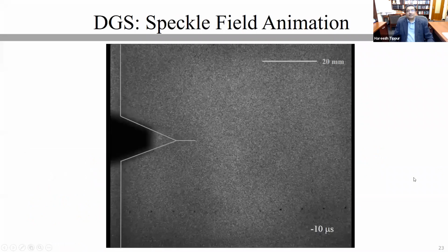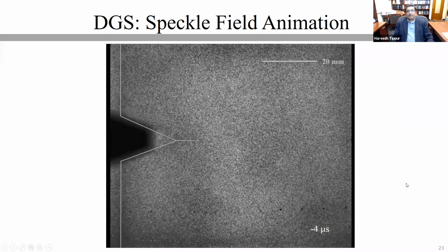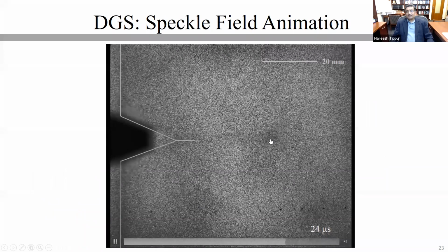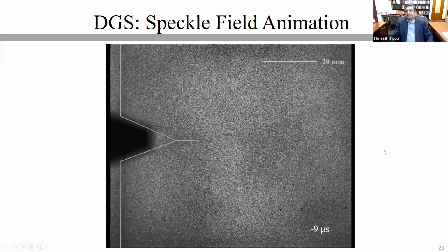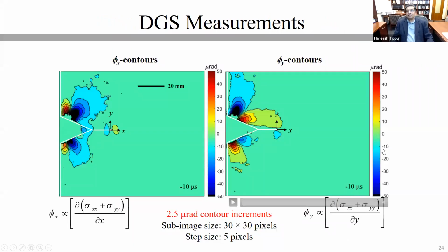Let me show you a little movie of the animation that you can make out of these images. When I run this movie, all you're looking at is the speckles on the target plane. There is nothing very exciting going on, as in the photoelasticity experiment, because all you're looking at are slightly distorted speckles. The only thing you see are little blobs of distorted speckles traveling along the potential crack path. There is not a whole lot you will see by simply looking at the images themselves, but you can certainly go back for post-processing.